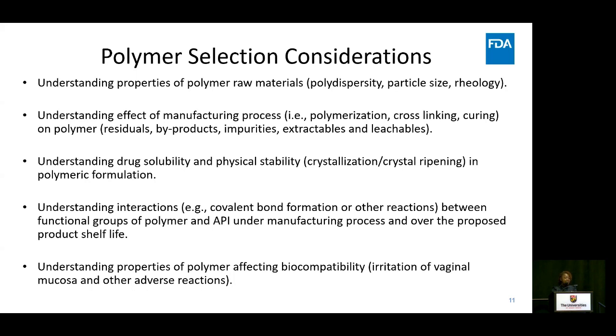And we also recommend applicants demonstrate understanding of the manufacturing process of the polymer as well as the final vaginal system when it comes to cross-linking or polymerization, the type of curing process that is used, and its impact on certain impurities that may be present, specifically extractables and leachables, impurities and byproducts, residual monomers. It's also highly recommended that applicants consider the drug solubility and physical stability within the polymer over the shelf life. When we talk about stability, we're talking about the propensity of it recrystallizing out or crystal ripening happening during the formulation, manufacturing process, or over the shelf life of the drug product.